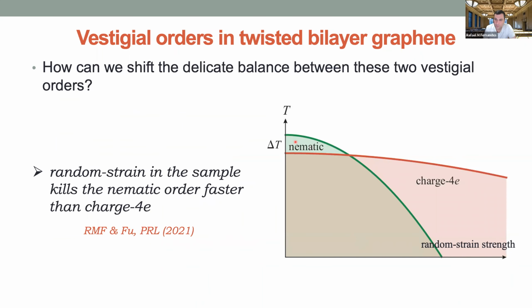There's a symmetry that says that they are nearly degenerate. So if there is a way of suppressing the vestigial nematic phase, the expectation is that the charge-4E phase will show up. This is all rooted in a hidden discrete symmetry called a perfect shuffle permutation symmetry.